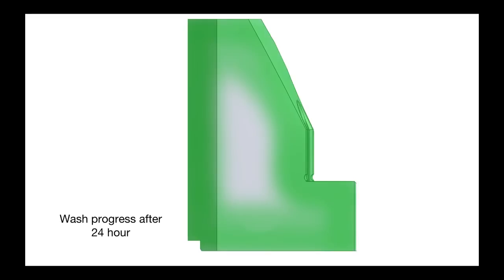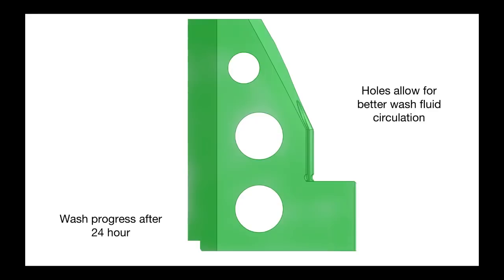So what we can do to optimize for wash times is add holes or channels to allow that fluid to circulate and touch internal sections of those features much faster. You will have to balance whether this is functionally appropriate for your part. Obviously, if I'm taking away material from my part, we want to make sure it's still strong enough. But in cases where that's fine, you can add channels like this to really allow the wash fluid to get into the center of the part, and you can speed up that wash process. And you can see this part has been fully washed after 24 hours.